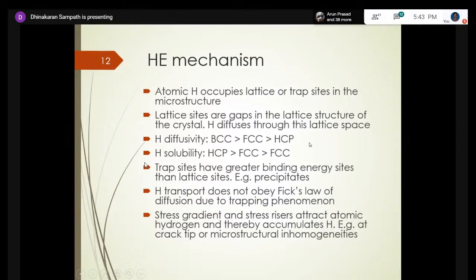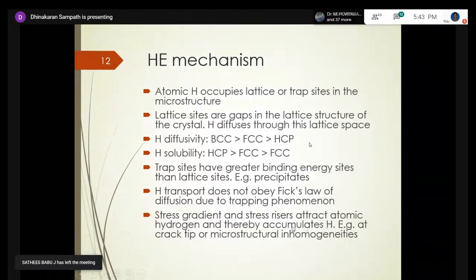And because of this trapping phenomenon, hydrogen transport doesn't follow Fick's law of diffusion, so we can't use that. There are many models, starting from the Oriani model, which account for trapping as well, to understand how the hydrogen transports. And also, stress gradients in the material, such as stress risers, attract hydrogen, thereby accumulating lots of hydrogen. That means at the crack tip, hydrogen accumulates a lot.